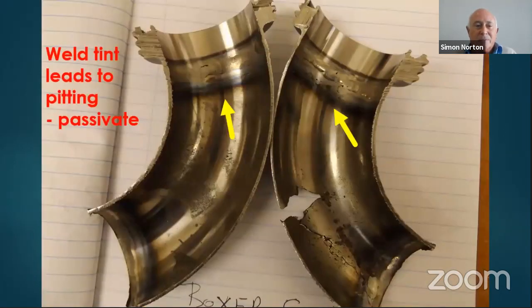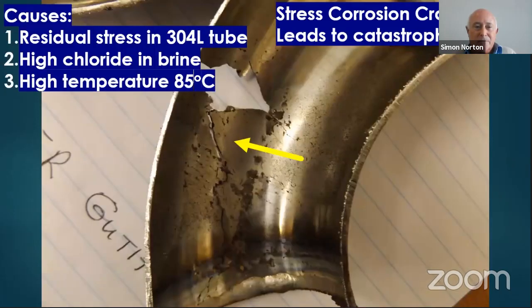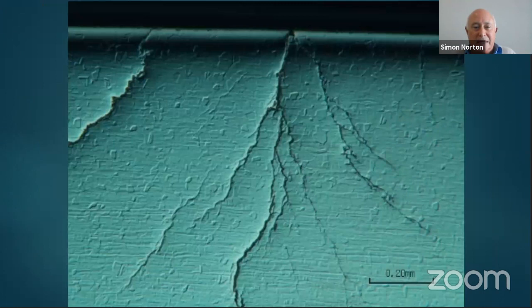Arnold's going to talk about this in a minute, but if you allow your stainless steel to become covered with oxide, you're going to sacrifice your stainless steel, because where the heat tint occurs, you get depletion of the chromium in the stainless steel and the destruction of the stainless steel. This particular pipe also suffered from stress corrosion cracking, which I'll talk about a bit later. That just gives you an illustration of what it looks like. Well, I'm going to hand over to Arnold now and come back to you later. Thank you very much.